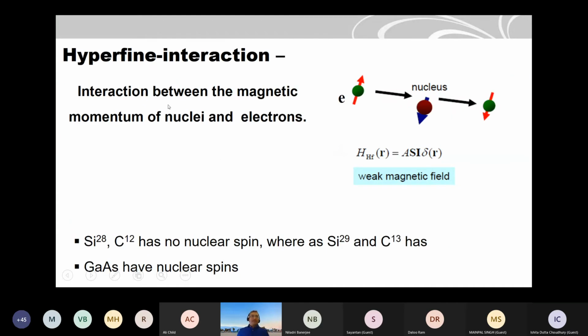And lastly, there is hyperfine interaction, when the electron spin interacts with the nuclear spin. So if your atom has a nuclear spin, then it will flip the spin polarization of the electrons. For example, silicon-28 and carbon-12 have no nuclear spin, but if you have silicon-29 or carbon-13, they have nuclear spins. So they can flip your electron spin polarization. For example, gallium arsenide also has nuclear spins. So this is not good for spin transport, but I'll show you results about that.